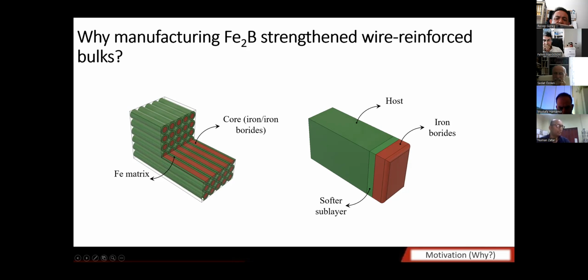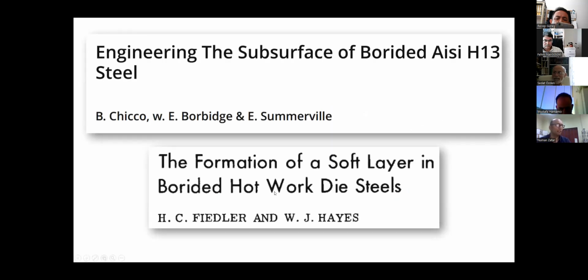These are my wires, and this as a whole is a wire reinforced composite. A surface-borided part will eventually fail when the wear of the top surface is gone. This will allow a continuous supply of iron boride phases during wear applications. And this material is not only for wear applications, it is also used as wire strengthening, as composite metal matrix strengthening. Okay, here is the proof.